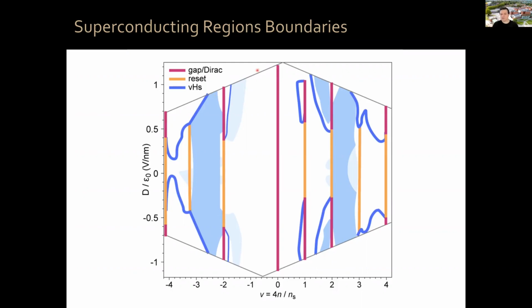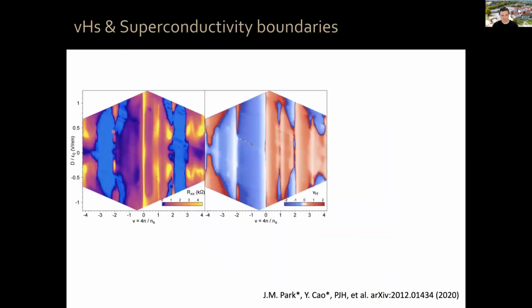As you can see, if you want to look for where superconductivity occurs and what the boundaries of the superconducting phase are, superconductivity occurs mostly between -2 and -3 and between 2 and 3, but also at large displacement field it occurs, for example, between 1 and 2, or between -1 and -2. And it sometimes does not occur in some regions between 2 and 3. What captured our attention most about this diagram are these types of boundaries. It turns out that in certain regions, superconductivity is bounded by Van Hove singularities. Let me show you this now in the actual data.